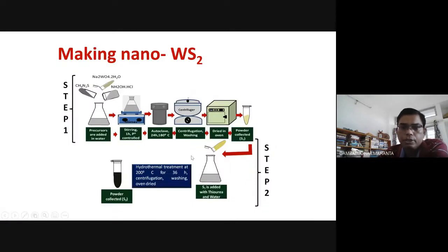Okay, this is a simple procedure for obtaining nano WS2 system. Out of many systems, one or two I would show, and I will focus more on the properties. Like you do in a chemistry lab, start with thiourea, then sodium tungstate, in acidified ammonia solution, stir to maintain pH, and then take this precursor into an autoclave. You know, an autoclave is a system in which we allow reaction in a controlled environment. Then repeated centrifugation, washing,